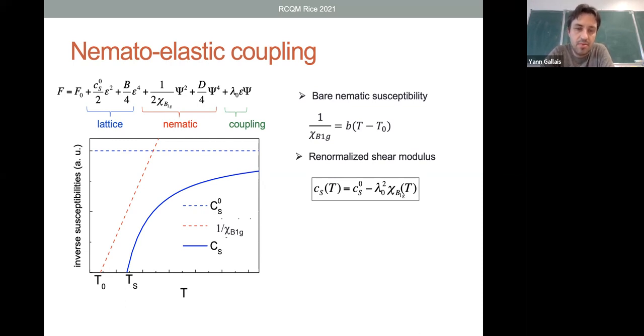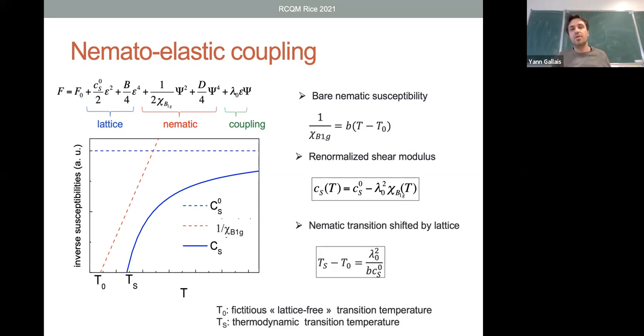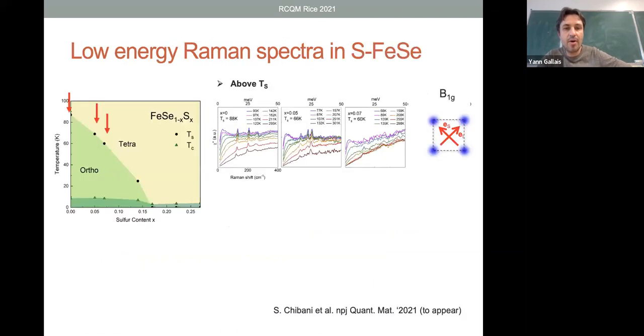Whereas T naught, which is located at lower temperature, is the fictitious electron-only nematic transition temperature. It's the transition temperature at which the system would transit if there was no lattice. And the coupling to the lattice actually stabilizes it to a higher temperature. So the difference between the two transition temperatures, TS and T naught, is set essentially by the square of the nematoelastic coupling. Okay, that said, what happens when you dope with sulfur? So this is the evolution.